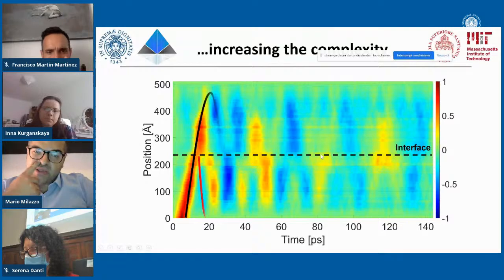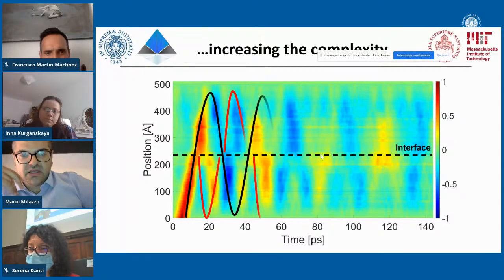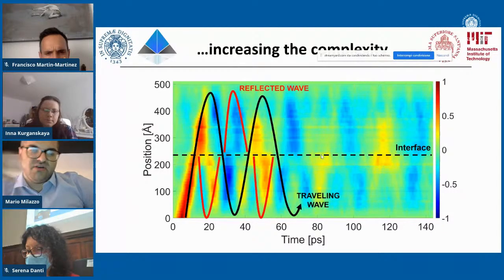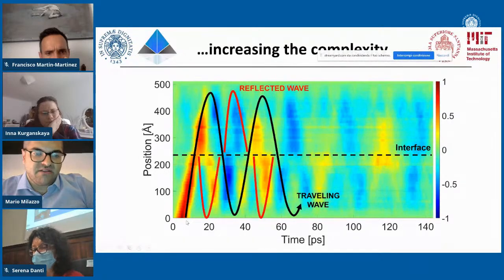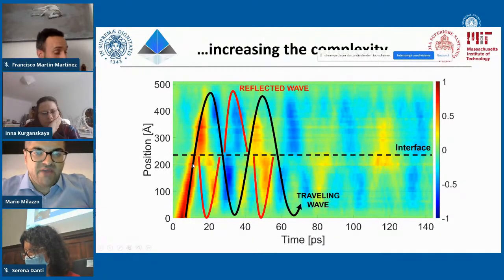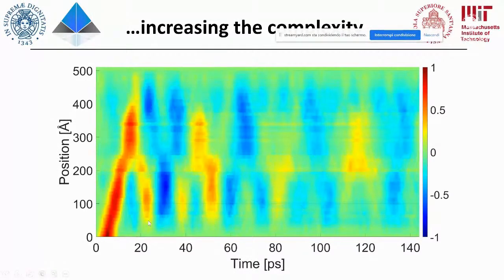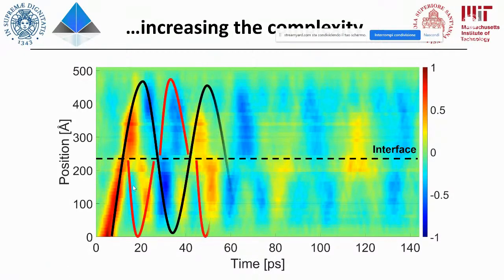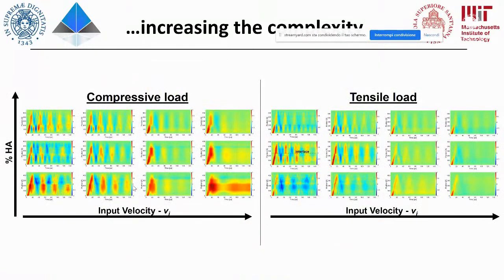And here, before showing you all the plots, here's a nice video in which I can show you qualitatively, because of course waves are not sinusoidal, but it's just a qualitative simulation of what's going on. You can see that there's a traveling wave starting from where the load is applied, and when the wave hits the interface between the two regions, the overlap and the gap region, we have a reflection of the wave. I can show you again. There's a reflection of the wave that creates a simultaneous rebound of the waves. This is really interesting because you can see it in both compressive load cases and the tensile load cases.